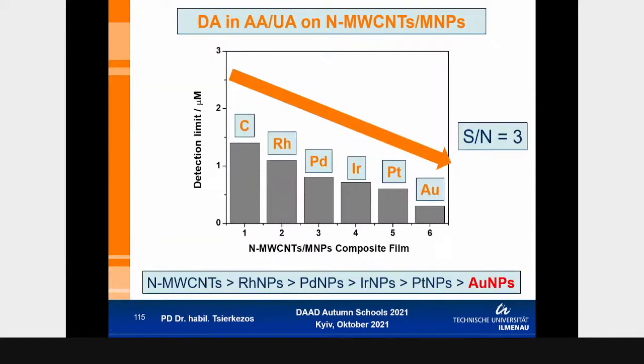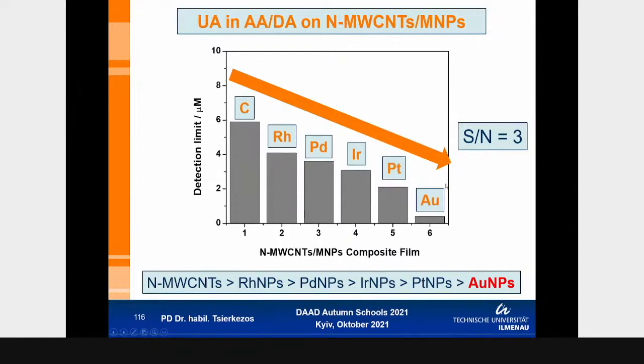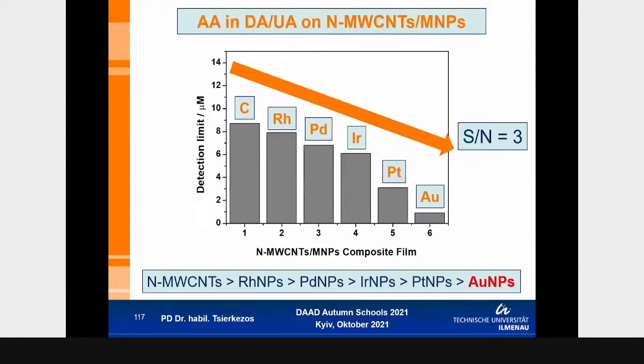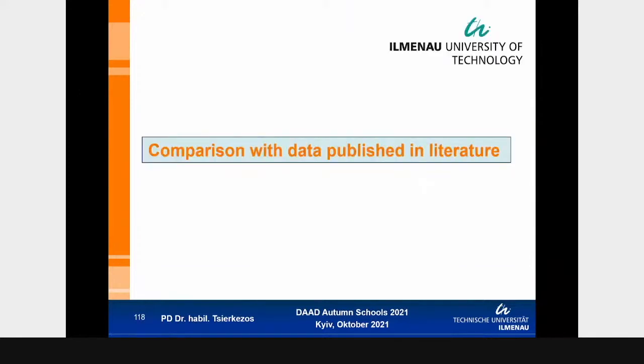So you can see once more the variation of detection limit of dopamine in the mixture with ascorbic acid and uric acid by using various nanoparticles. The first is the unmodified nitrogen carbon nanotubes, then modified with rhodium, palladium, iridium, platinum, and gold. The same with the variation of uric acid and the detection of the uric acid, and the same the variation of detection limit of ascorbic acid. So in all cases, we observe that gold nanoparticles is the best material on modifying the carbon nanotube to nitrogen carbon nanotubes for detecting the biomolecules.